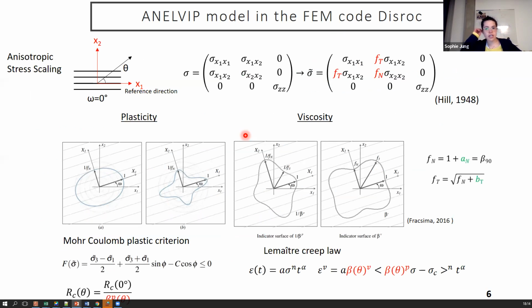First, I'm going to present the model used in the numerical simulation. It's the model ANEL-VIP, which is already present in the FEM code DISROC, and it's a threefold anisotropic model. The elastic, plastic, and viscous parts of the constitutive law are transverse isotropic. The plastic and viscous anisotropy are managed by anisotropic stress scaling, as introduced, but at the time only for plasticity, by Hill in 1948. The anisotropy is defined by two plastic parameters and two anisotropic creep parameters.